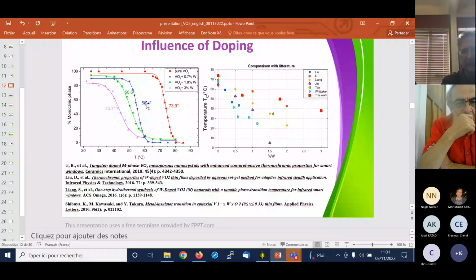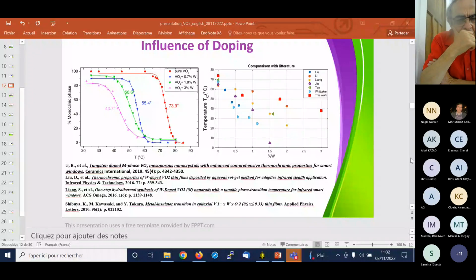I already put my questions on the chat, which I will just start now. It relates to the distribution of your tungsten within the VO2 structure. Since you're starting with the layers, it's more like a multiple layer system. How is the distribution when you're annealing at about 400? Is it 450 or 400? 400. How do you monitor the distribution?